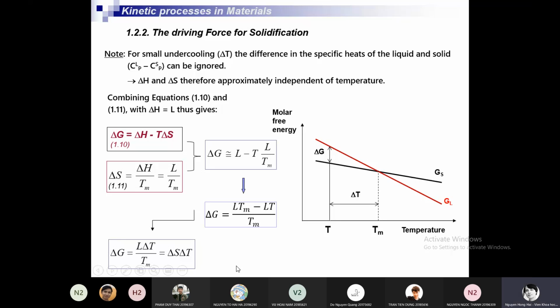See? So the conclusion here, we can say the driving force for solidification is proportional to the undercooling. The greater the undercooling, delta T, the greater the free energy, and the quicker, the faster the transformation can occur and proceed. Because this is the driving force for solidification. So if the driving force is greater, the process can happen faster, and because it's proportional to the undercooling, the greater the undercooling, the faster the transformation.